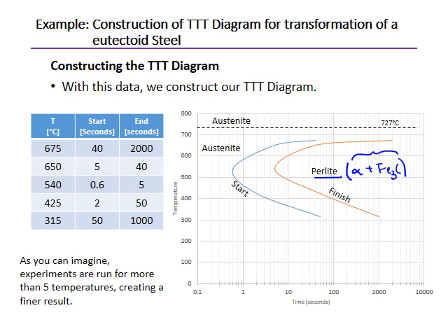That's not the case for the eutectoid steel, because the eutectoid steel has the eutectoid composition, so there is no possibility for primary phases. So you will reach the invariant point, and from that invariant point you will get directly pearlite. So there is nothing in the middle.